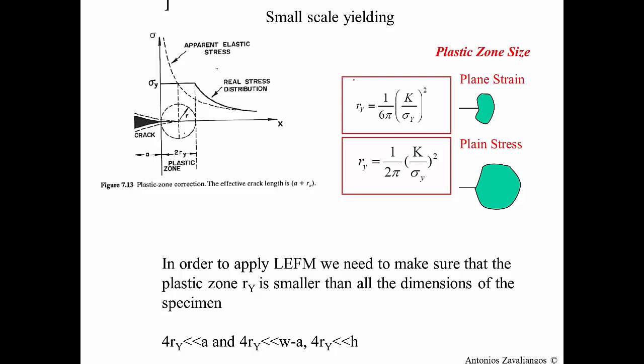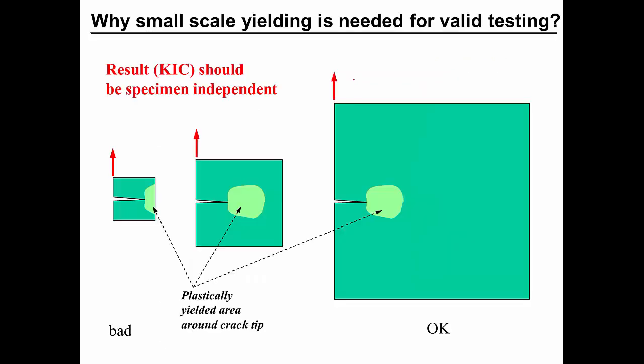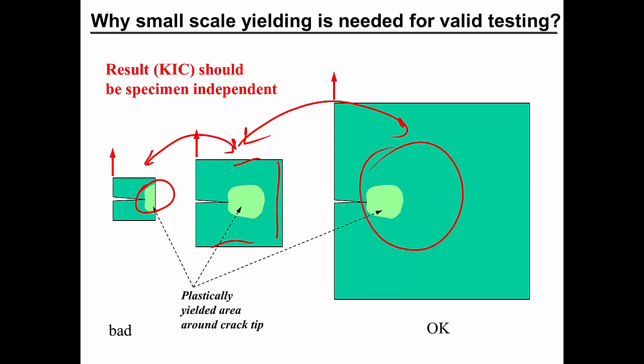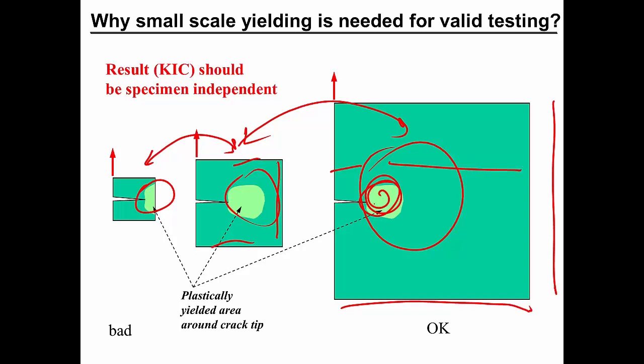These are the equations that I was talking to you about in the previous slide. So why is small-scale yielding needed for valid testing? You can probably see this here in a qualitative argument. If there is a lot of plastic zone in this range, you can see that this kind of test and this kind of test are really not equivalent. This one and this one may be equivalent, assuming that the presence of the boundaries does not interfere substantially with the stress field around the crack tip. This is satisfied when this plastic zone is much smaller than the in-plane dimensions of the specimen. This one, this one, this one, and that one. So we want this plastic zone not to interfere with the boundaries of the specimen.